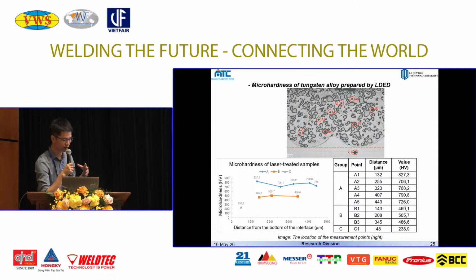Other than that, we also did microhardness measurements. We measured the base material, the mixing area, and inside the tungsten particle as well. We can see here, of course, the base material has very low hardness. Higher than that is the tungsten particle. The mixing zone has the highest hardness here. It is actually because of the intermetallic structure.